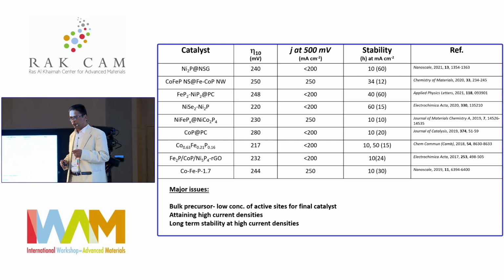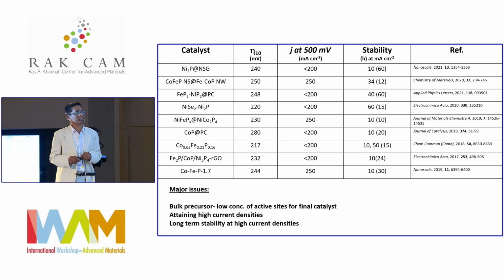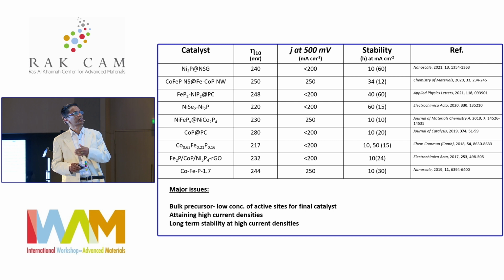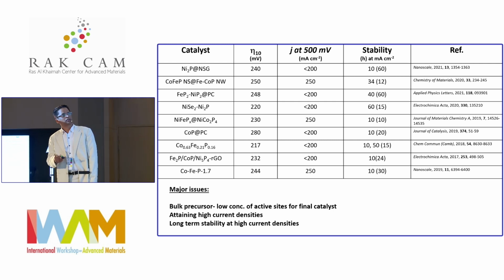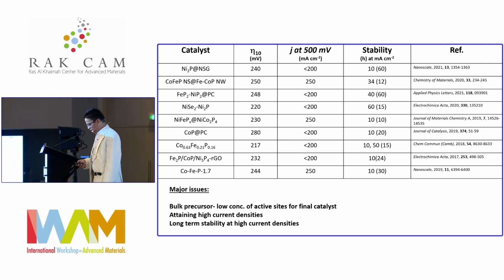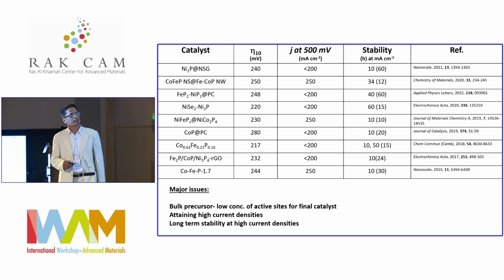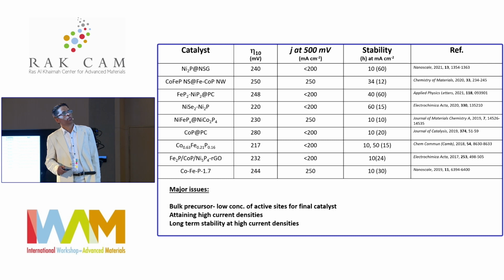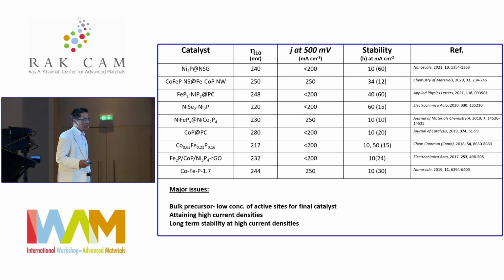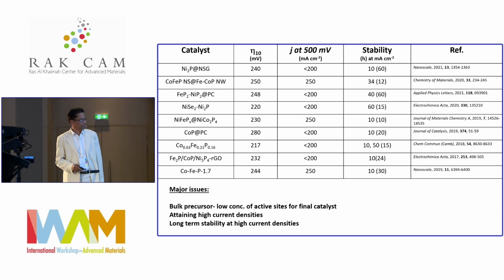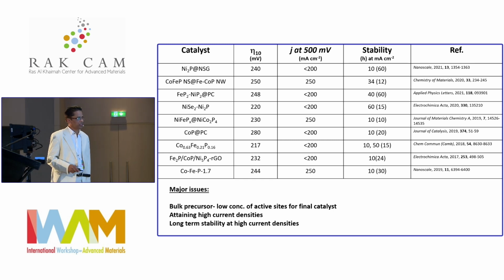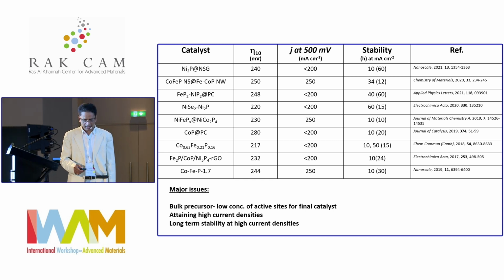Even for an industry level, you have to look at at least 1 ampere per centimeter square current density to think about anything at industrial scale. And also stability is not too high, except for 10, 12, 20 or 30 hours. One problem is that they use a bulk precursor, with a low concentration of active sites in the final catalyst. Reaching high current density is a big issue, and long-term stability at high current density is challenging.